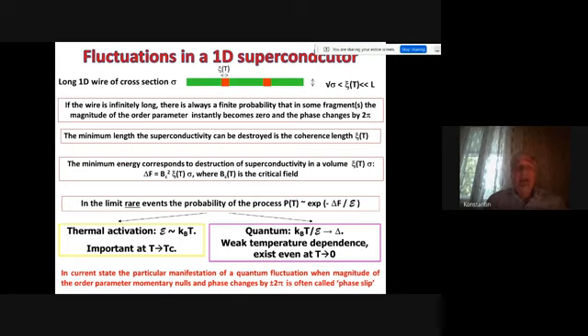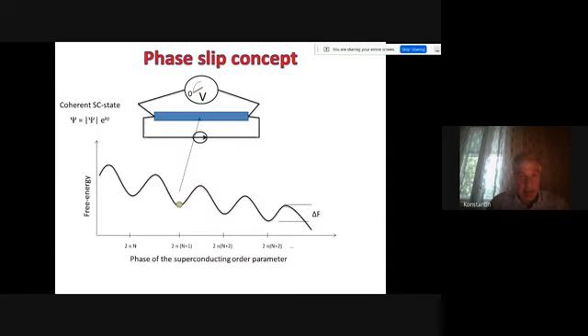If we now apply current to such a system where the fluctuations happen, it appears that there is a specific type of superconducting fluctuation. I will mainly speak about this later. The superconducting order parameter momentarily goes to zero and the phase of the superconducting order parameter is changed by plus or minus 2 pi. This type of fluctuation is often called a phase slip.